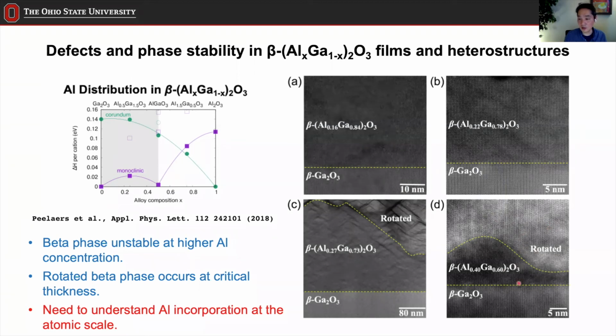Okay, so what that means is this is a realistic critical thickness, and this essentially has become the critical concentration, only 40%, which is way lower than what was predicted here. So what's the reason for it? And that puzzled everybody, and then we were trying to find the answer for it. So the answer might be related to the fact that the calculation here, if I'm correct, Hwang, I think, was assuming an equilibrium state, mostly about bulk, and therefore at that equilibrium assumption, all the aluminum atoms should be occupying octahedral sites. I think that's assumed here.